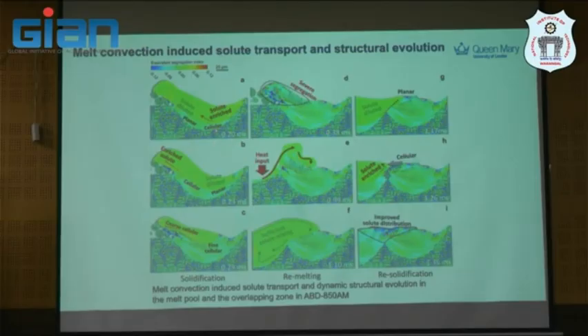Planar and cellular structures will form, and after that, as this progresses, the solute enriched zone goes up and leaves behind the solute dilute zone. Then the cross structure, due to the fluid flow as well, gives this cross structure. And you get the severe segregation profile here. After that, once another heat input is applied, this is the first track, right? For the second one, in the overlap zone, the heat input will push away this solute because it will be remelted again. This zone has been remelted, and there is sufficient solute mixing. It's mixed together, and this leaves behind a solute dilute zone, so there is no heavy segregation here.